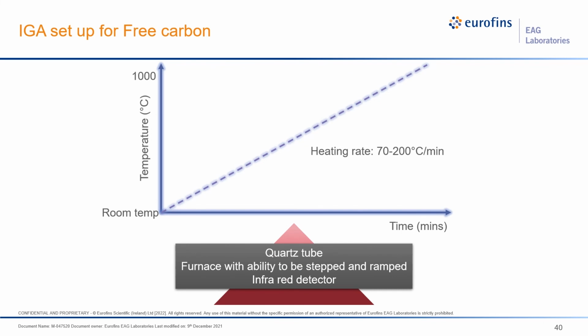To perform free carbon analysis, there are some prerequisites. The heating should be done in quartz tube instead of using the more common ceramic tube or crucible. This is because ceramic, due to its permeable nature and structure, can interact with released carbon and could affect the final measurements. The other prerequisite is using a furnace where temperature can be raised by following a specific heating rate. This is usually done with a precision of plus or minus 5 degrees Celsius by using a programmable temperature controller. Such a furnace would enable us to perform heating in steps and with desired ramping. Generally, for detection of free carbon, we use infrared detector.